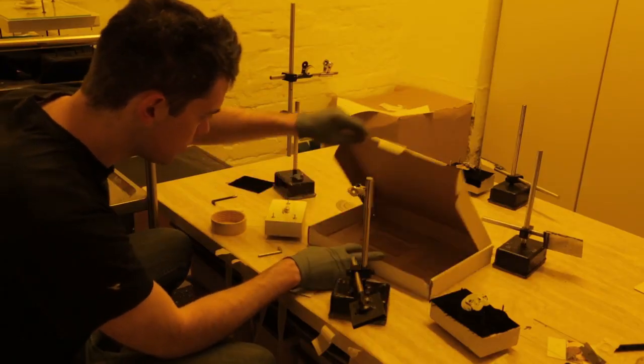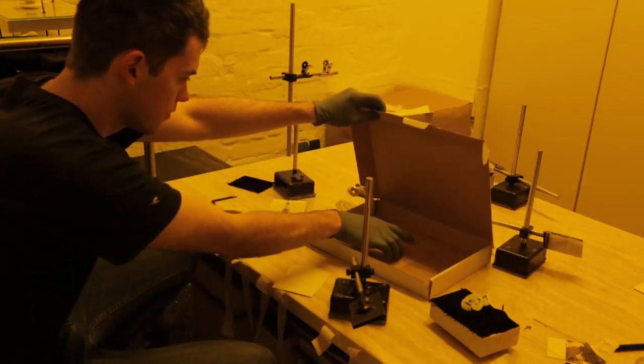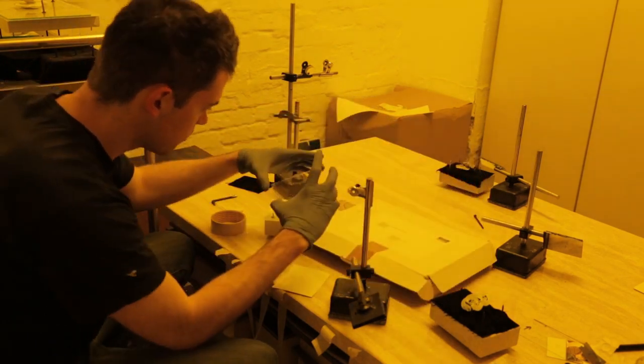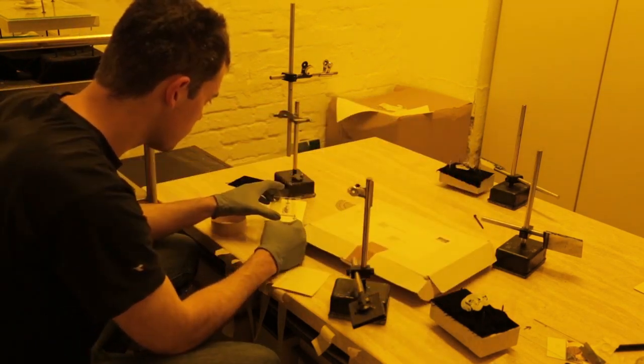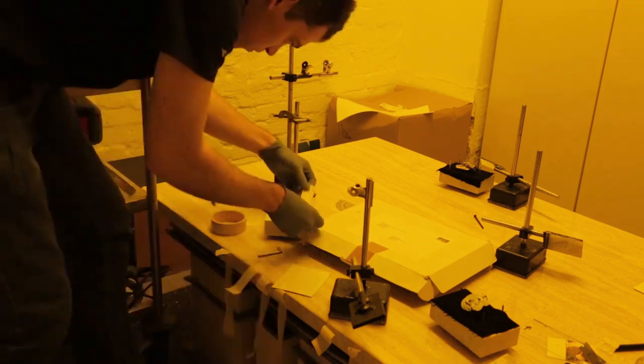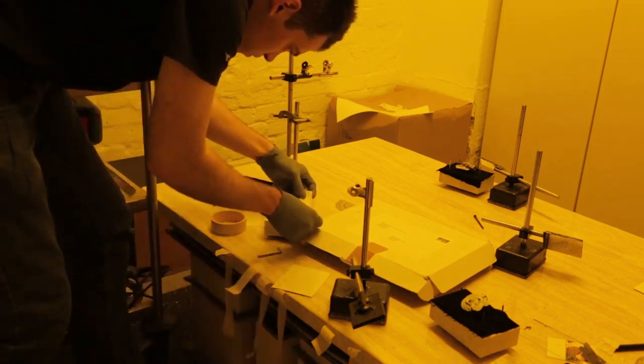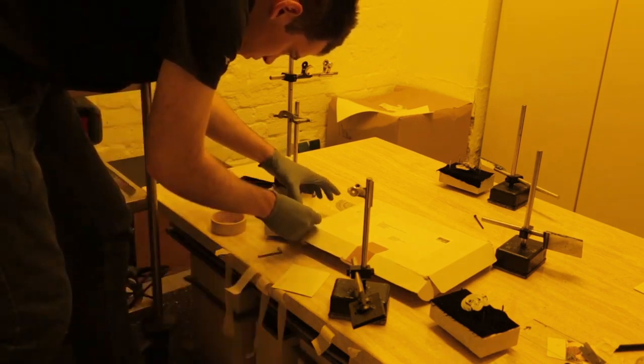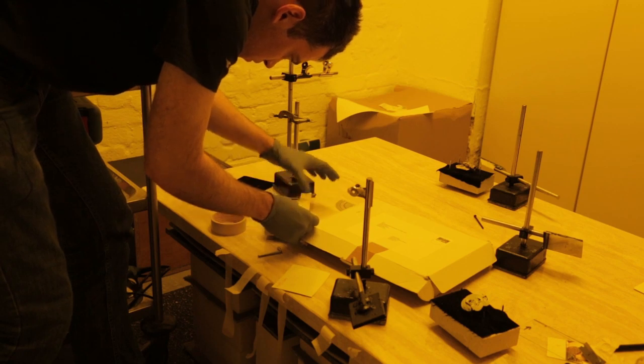I place the brush handle under the glass, apply pressure on both sides, and thus facilitate the break of the glass. In a light-tight box, I transport the plates to the exposure room. In the exposure room, the humidity should be at 60% and the temperature at 24 degrees. I put the plate emulsion side down on the exposure setup.